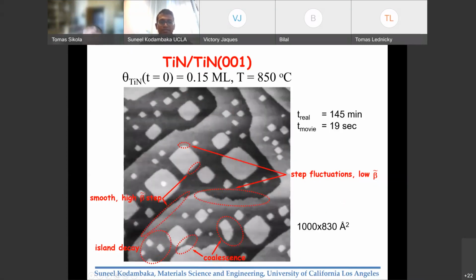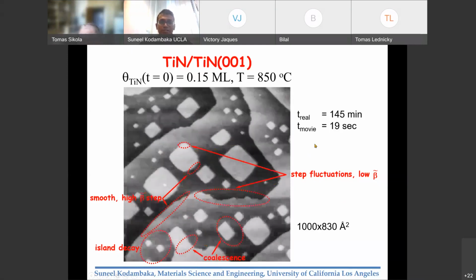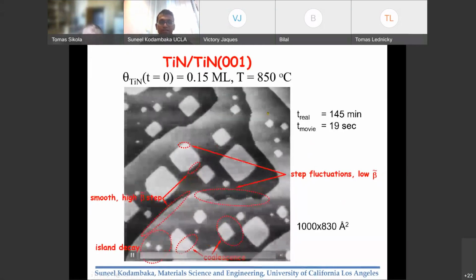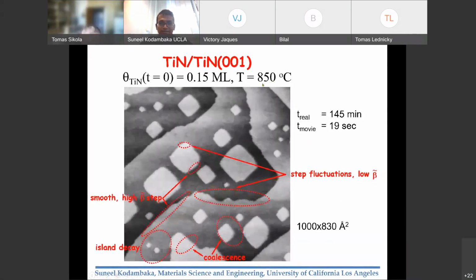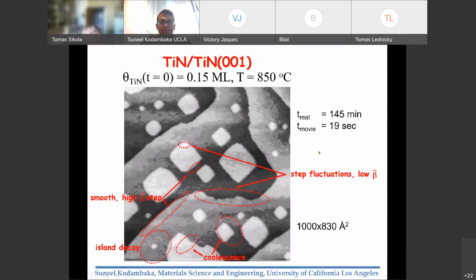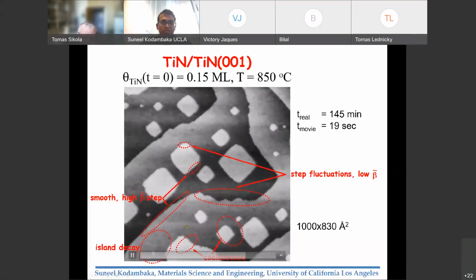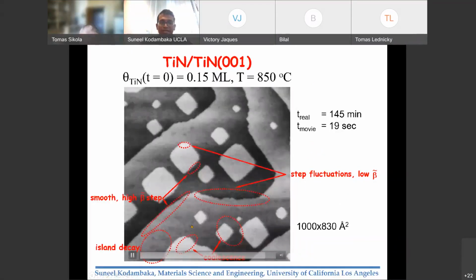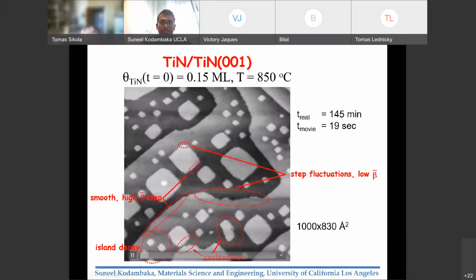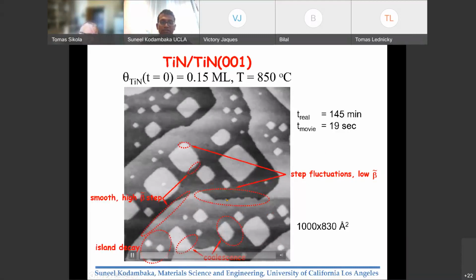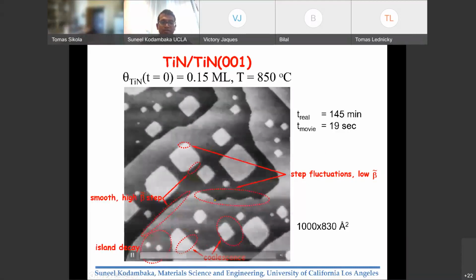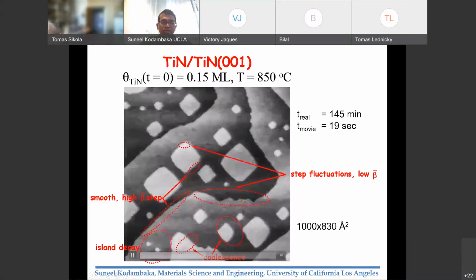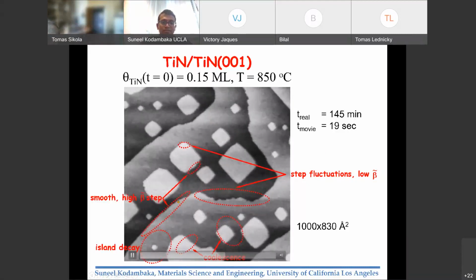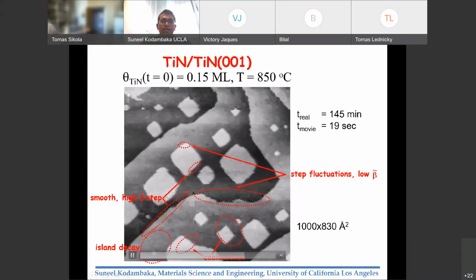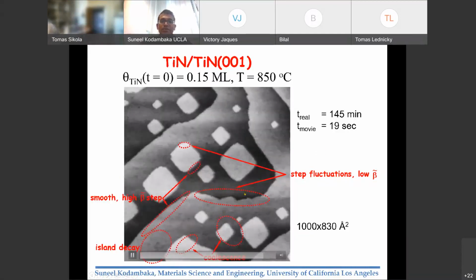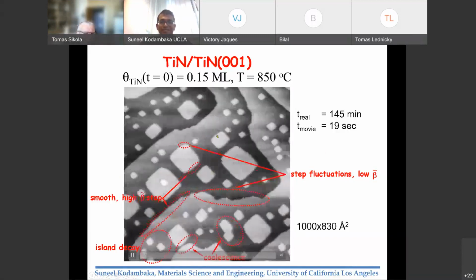Okay. So this is a time-lapsed STM images that are compiled together as a movie. And this is obtained while scanning the sample at 850 degrees Celsius in the STM. And so as time progresses, you probably have seen a lot of these smaller islands disappear. Some of the larger islands coalesced, and you will see these fluctuations in these step edges, whereas the fluctuations are more at certain oriented step edges compared to the other steps. Okay. And I'll talk about how to use this information to extract fundamental parameters pertaining to this system.